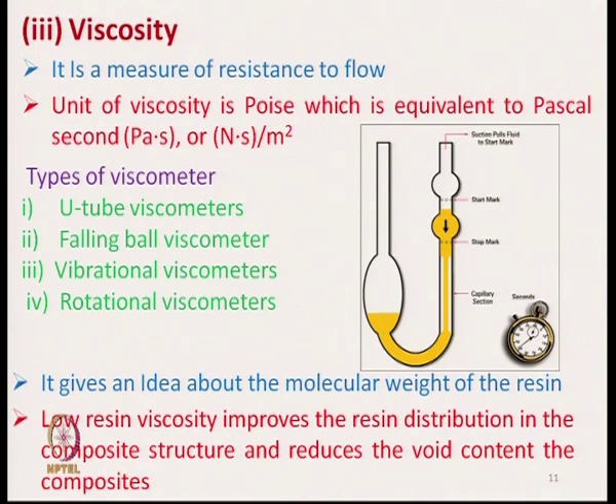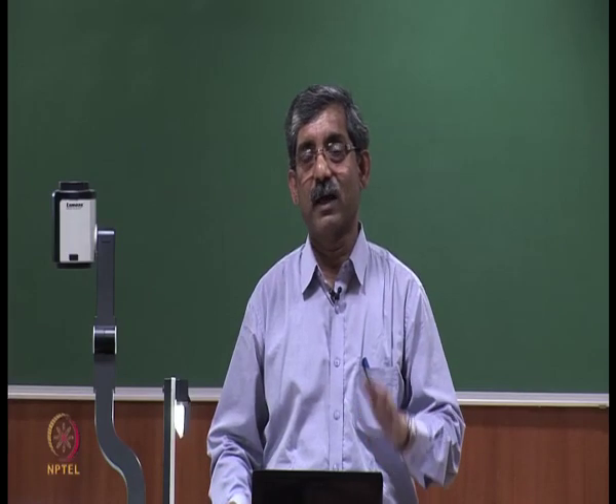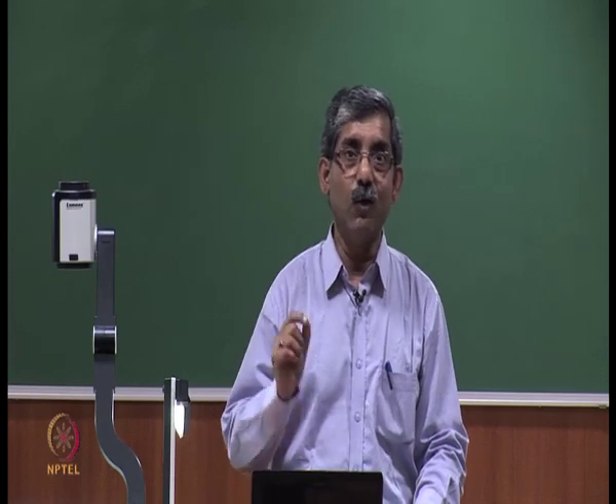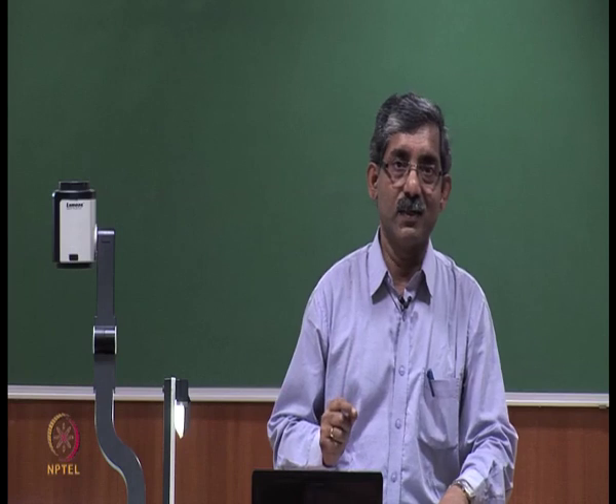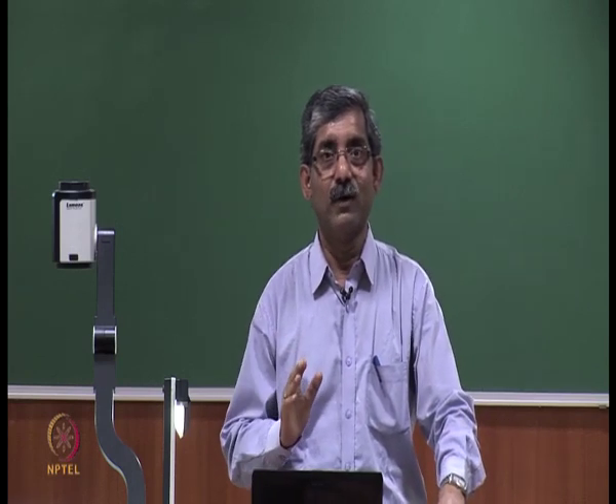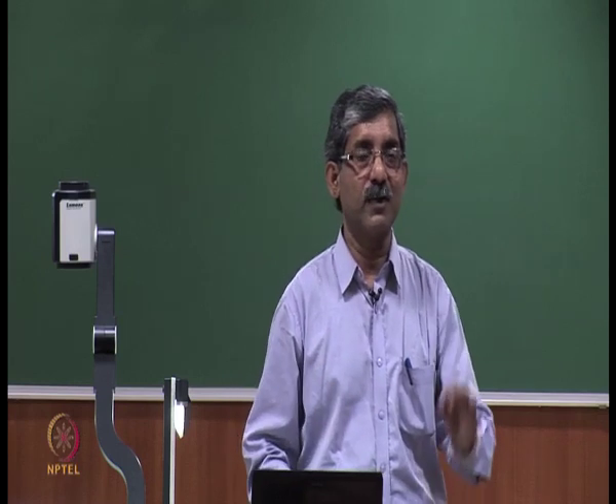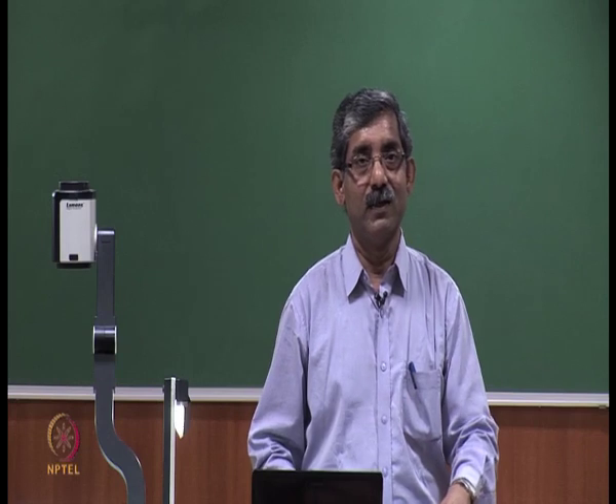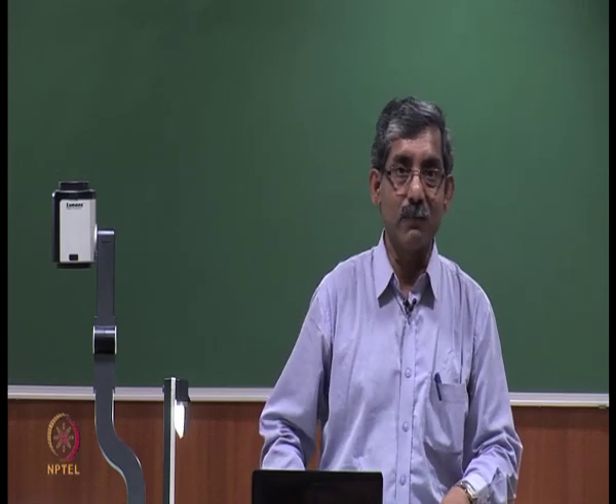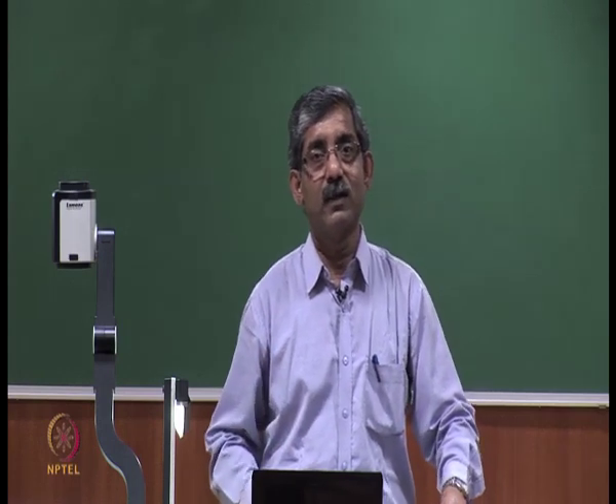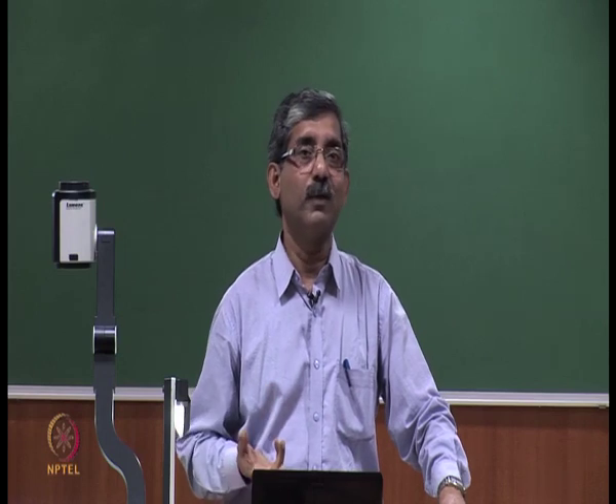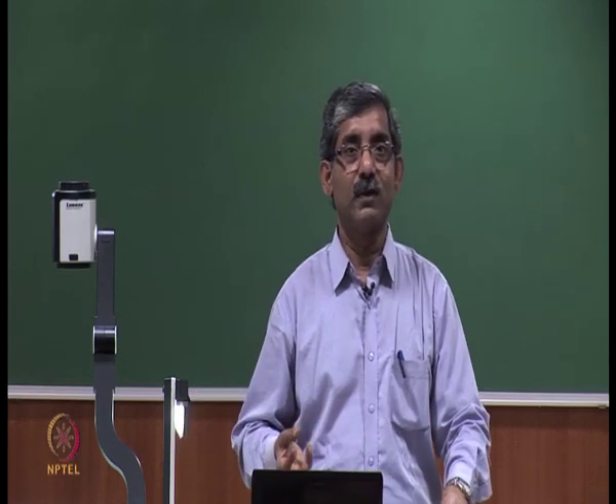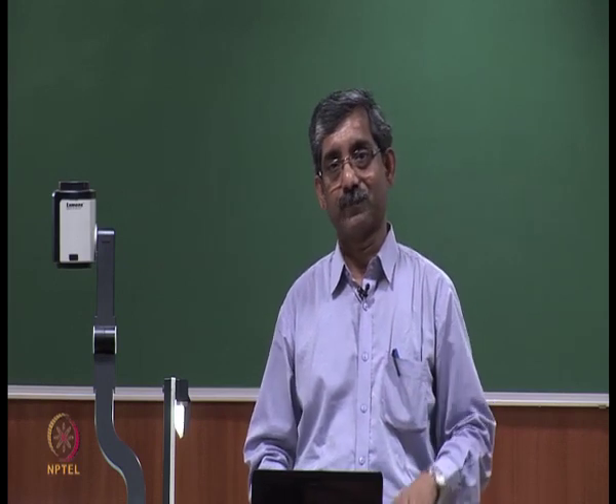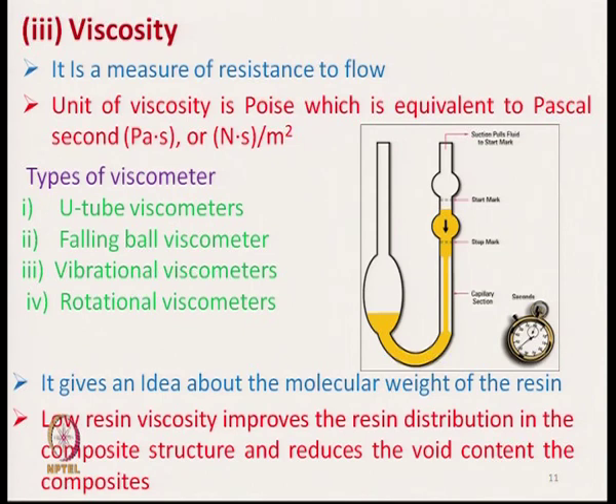Next is the viscosity, which is an extremely important characteristic of any matrix material. As I have mentioned, at low temperature the thermoset matrix has the advantage of very low viscosity. Low viscosity means the flow through the pores of the fiber, the penetration of the matrix material, will be easy. On the other hand, thermoplastic matrices at normal temperature are solid, like polypropylene. To reduce the viscosity we have to increase the temperature, and the viscosity of thermoplastic matrices is relatively high.